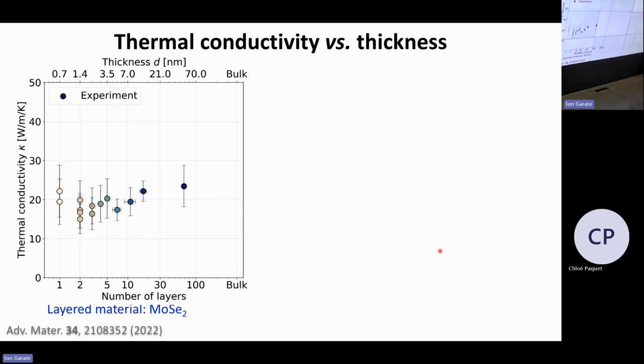This is the thermal conductivity of our layered material, molybdenum diselenide, as a function of thickness, all the way from almost 100 layers down to a monolayer. And what you see is that the thermal conductivity is almost completely flat. We start out with a few tens of watt per meter Kelvin, and it's still a few tens of watt per meter Kelvin, even at a monolayer.